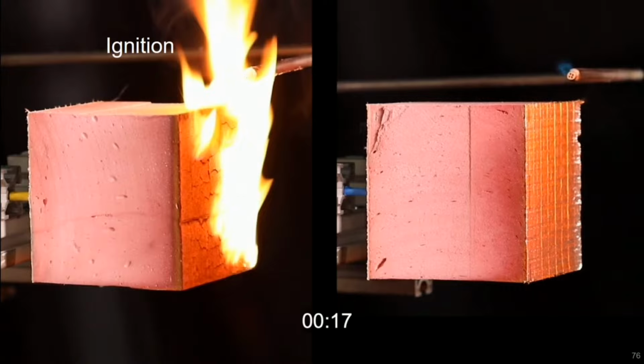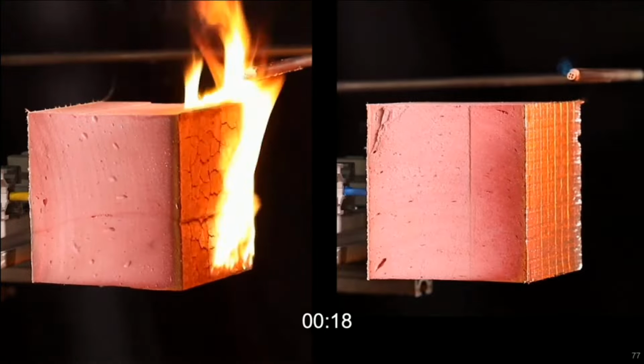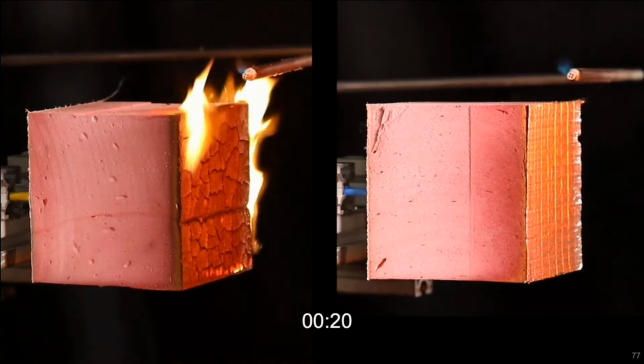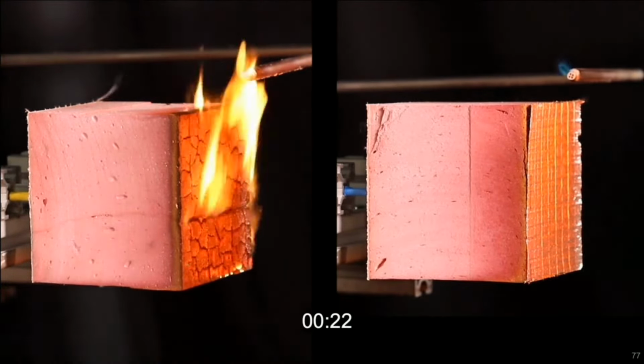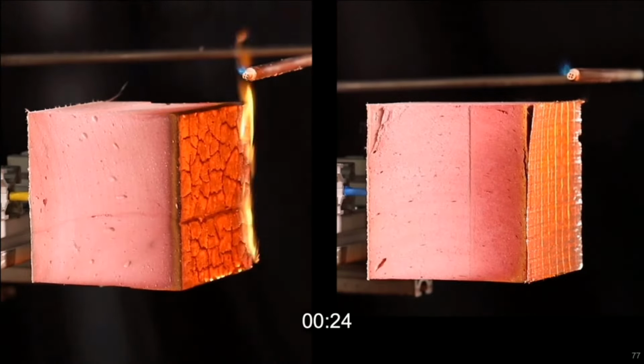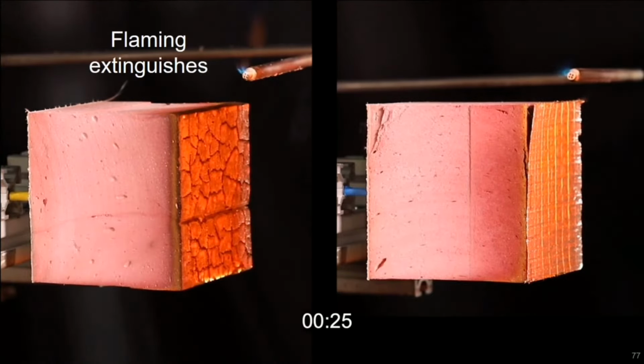So there we have ignition at about 16 seconds. Beyond ignition, there's no obvious melting or dripping from the sample, as I've mentioned. We can see the formation of a char layer over the surface of the sample and a reduction of flaming. Quite rapidly in this case, we get a reduction in flaming.